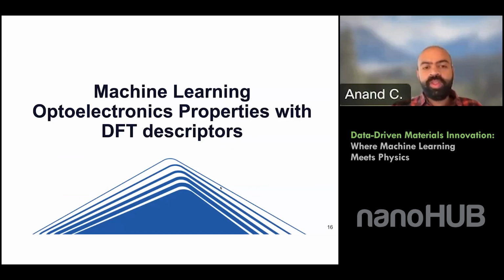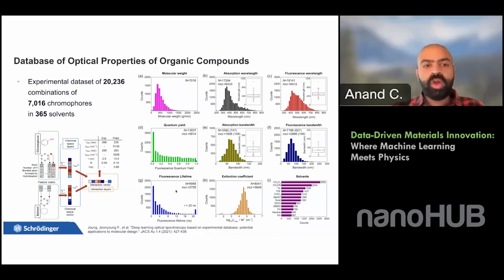So in this previous case study, I talked about how we obtain descriptors from molecular dynamics. Similarly, we can obtain descriptors using DFT. One particular case study here is a database of optical properties of organic chromophores, of organic compounds. These organic compounds and their optical properties are extremely relevant for photovoltaic applications and also for OLED devices. This excellent paper had a dataset of around 20,000 measurements, of around 7,000 chromophores in 365 different solvents.